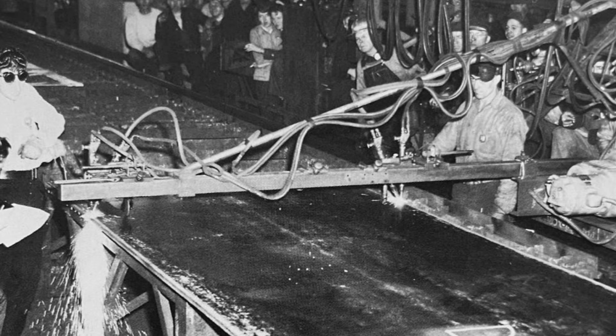Within seconds, a fracture raced from the deck down through the hull plating. The crack didn't follow the welds. It tore straight through the solid steel plate. The ship split completely in two. Her bow presumably sank immediately. The stern section drifted until it ran aground in Alaska. 10 men were lost.